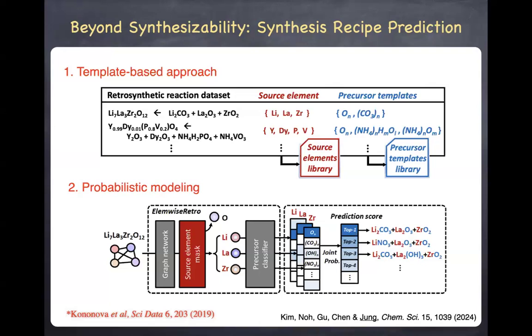And so if you look at this database curated by the Ceder Group, there are about 100, or of the order of 100, precursors that are often used. So instead of the model predicting the precursors randomly, we have a predefined list of precursors, like 50 to 100 of them. And the model is trained to select the correct set of precursors from the list. And we call that a template-based approach. And then you do some probabilistic modeling using some kind of graph convolutions.